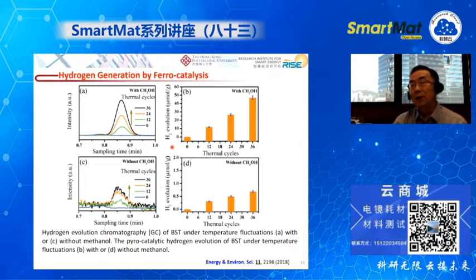We put these pyroelectric barium strontium titanate nanoparticles into the water. Then after the thermal cycling, we found the release of hydrogen, and we also compared two different cases. One case is without methanol. In this thermal cycling, there's no methanol being added. Then we found the hydrogen evolution is very small, and when we add methanol, we can greatly enhance the